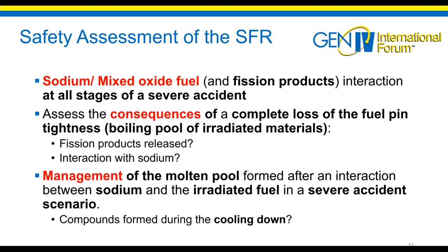Therefore, the scope of the study is really the safety assessment of the sodium-cooled fast reactors with different axes. The first one is the sodium, mixed oxide fuel and fission products interaction at all stages of a severe accident. You also have to assess the consequences of a complete loss of the fuel pin tightness. So what's happening when you have a boiling pool of irradiated materials? You have to answer basically two questions. Which fission products are released? And is there an interaction with sodium? And finally, you also have to manage the molten pool formed after the interaction between sodium and irradiated fuel in a severe accident scenario. So basically, which compounds are formed during the cooling down of the core.